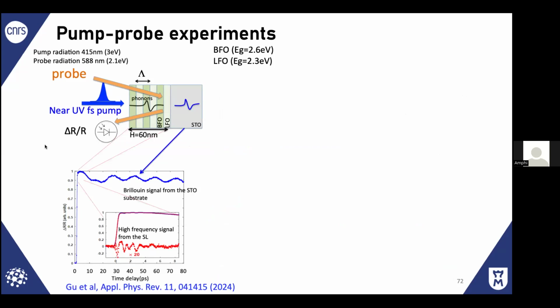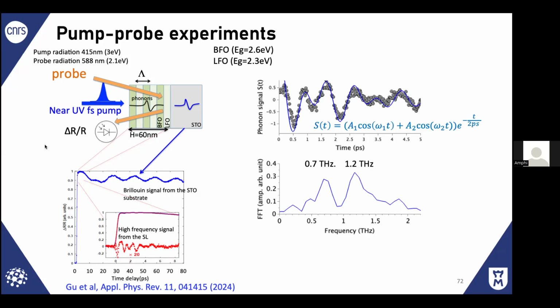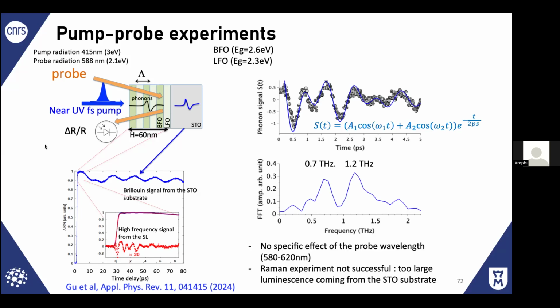There's a rapid increase of signal due to the creation of electron-hole pairs, and superimposed there are different oscillations. That oscillation at large time scales is due to the fact that there are phonons emitted. So you get just the Brillouin component of the substrate. But if you look at the short time scale, you see such a signal like that. And you have two components, 1.2 terahertz and 0.7 terahertz.